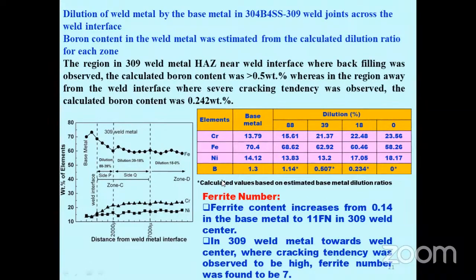So because of base metal dilution, we are having some region in the weld metal where the boron content is falling below 0.5 weight percentage, and it is prone to cracking. And this is very obviously the reason for cracking in these weld joints.